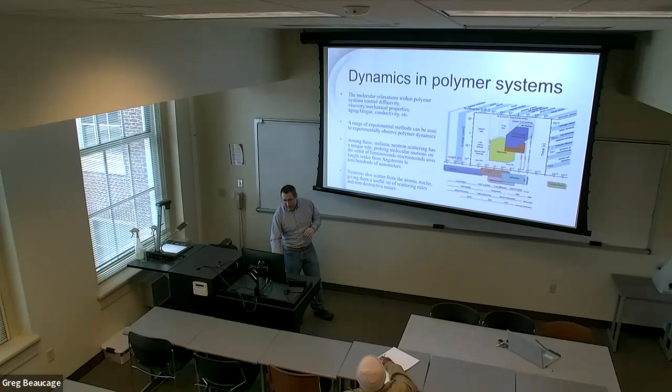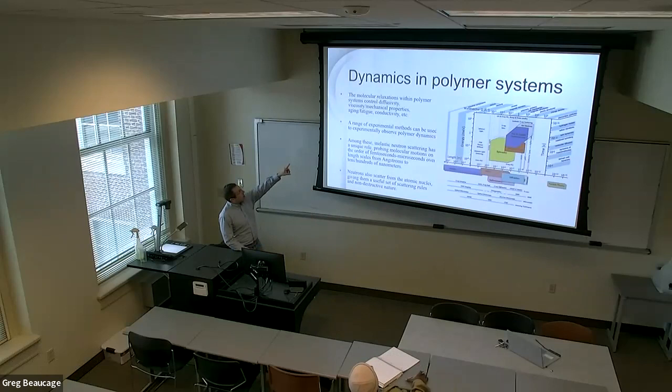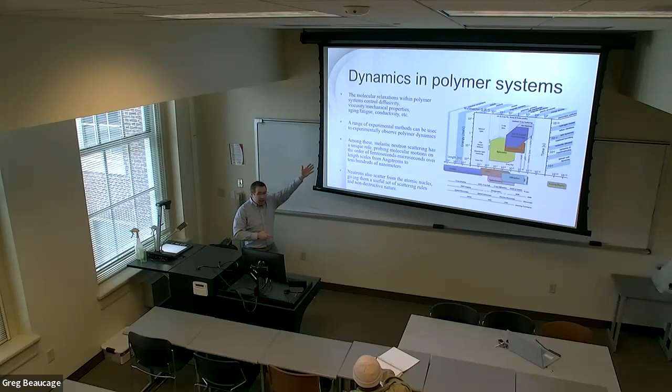Okay. So dynamics in polymer systems. Molecular relaxations within polymer systems control all of the physical properties, right? So the diffusivity within the network, viscosity and mechanical properties of the material itself, aging and fatigue. Slow relaxation processes, the untangling of networks or of interconnections, can lead to aging and fatigue. Conductivity, right? If you're thinking about polymer batteries, the conductivity is directly coupled to the diffusivity. If you have ions in a polymer matrix, they have to diffuse through the matrix to carry charge. That means the polymer dynamics control the conductivity. Okay, so all of these things make that concept really important.